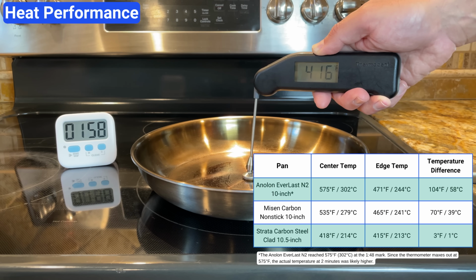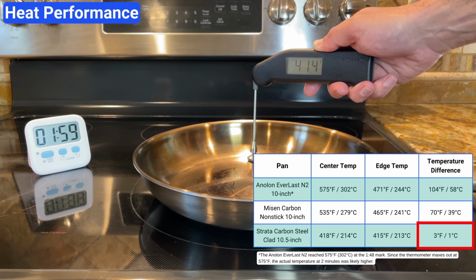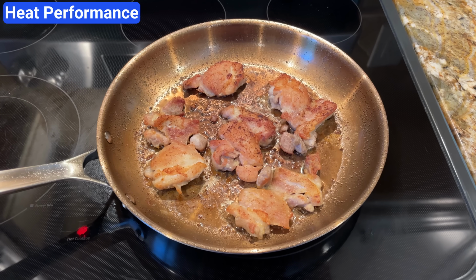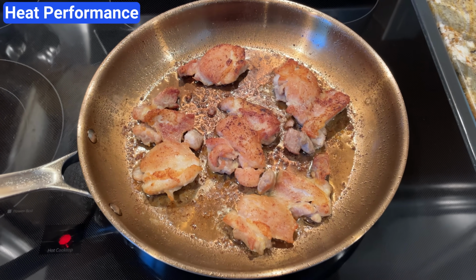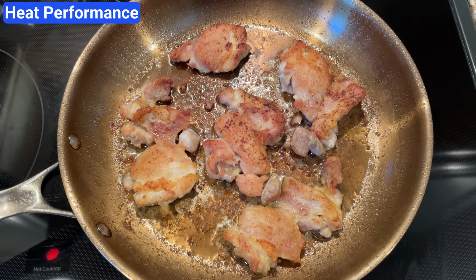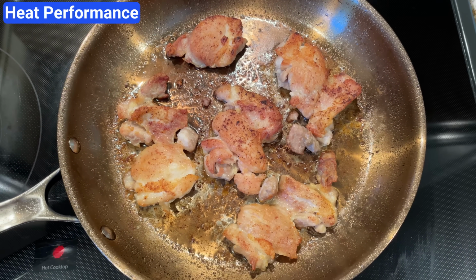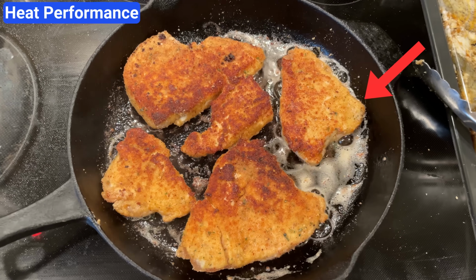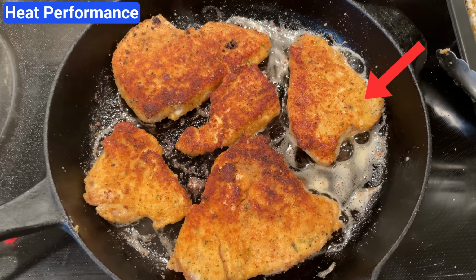Strata didn't heat as quickly, but it was the most even. After 2 minutes, there was only a 3-degree difference between the center and edge. And in real-world cooking, that evenness held up. When I cooked a full pan of chicken, the pieces around the edge browned just as evenly as the one in the center, which isn't always the case with cast iron or traditional carbon steel pans.